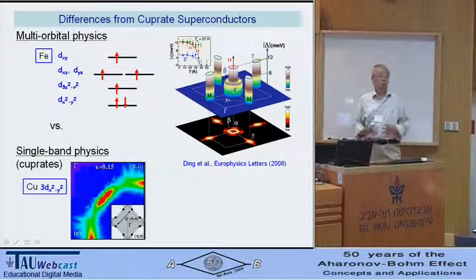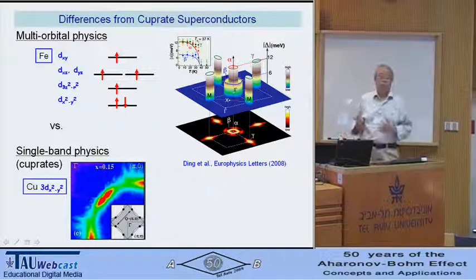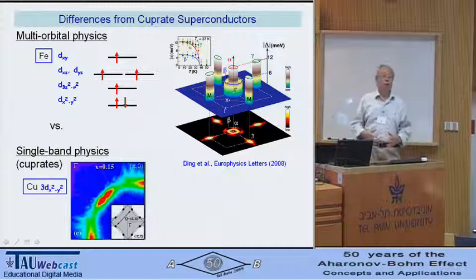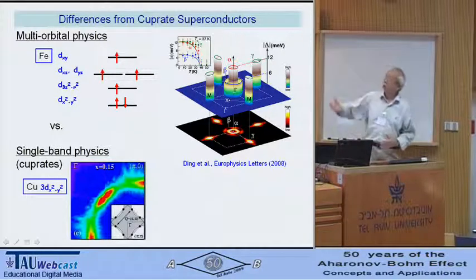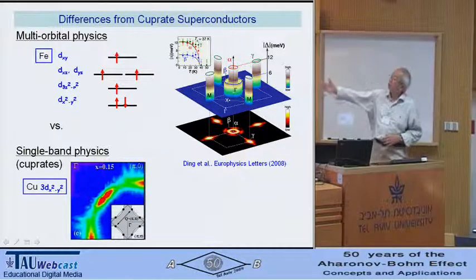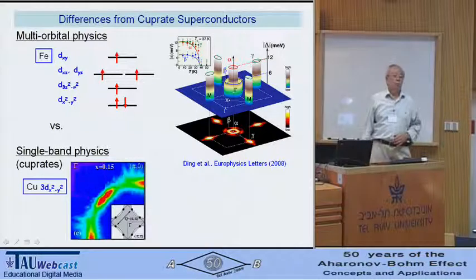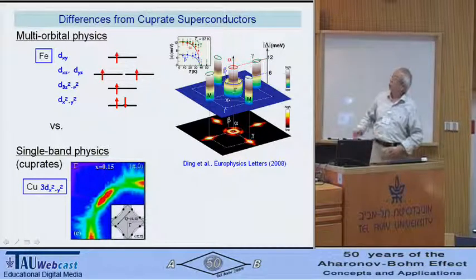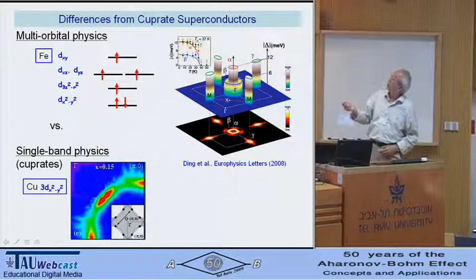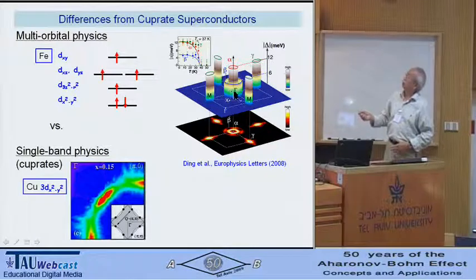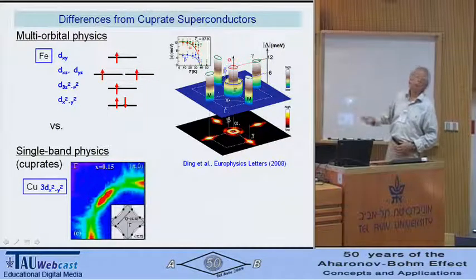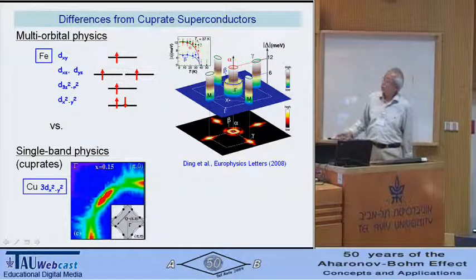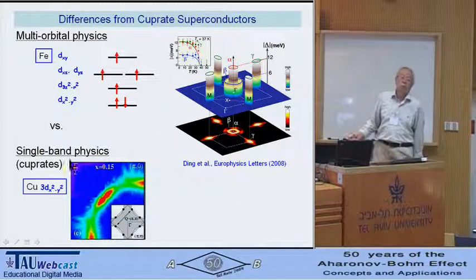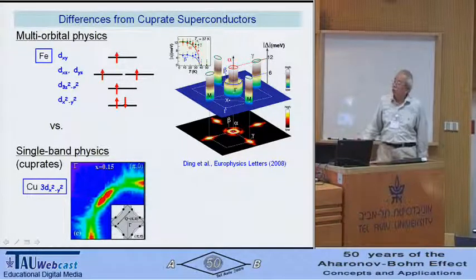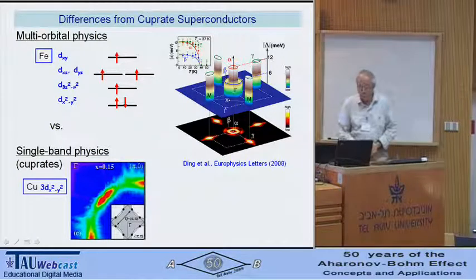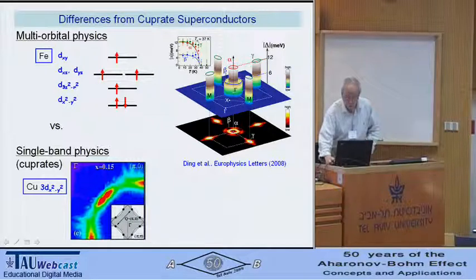Okay, what is the difference between the cuprate and iron pnictide? Basically, it's the band structure. In the iron pnictide, the band structure is derived from the iron d orbitals, as I indicated here. And sure enough, the photoemission result indicates you have multiple Fermi surface sheets. In the center, you have hole pockets, and then outside you have electron pockets. So totally five Fermi surface sheets. This is in contrast to the single band physics involved in the cuprate, where you have only one single band. So that's quite different between those two systems.